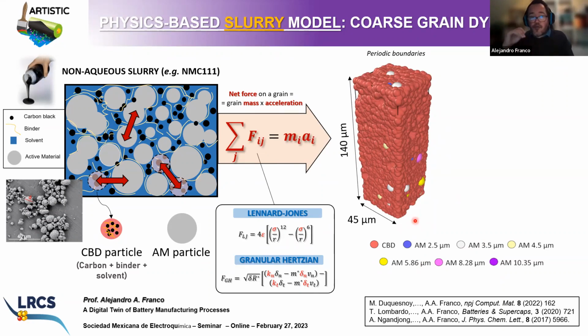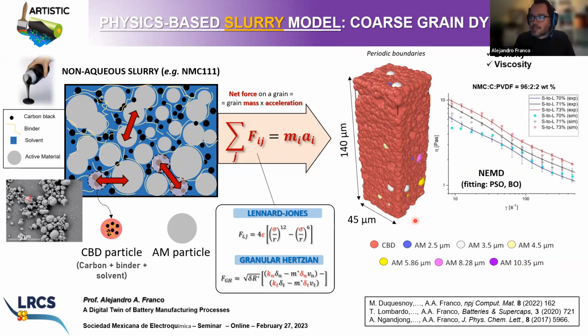Once you get this digital twin of the slurry, you can calculate in the computer properties that can be measured experimentally. For instance, the density of the slurry and the viscosity of the slurry as a function of the applied shear rate. And then with a lot of back and forth between the calculations and the experimental data, you can determine the parameters that you need to put in the force expressions, the force field expressions, in order to describe correctly the viscosity and the density of the slurry.